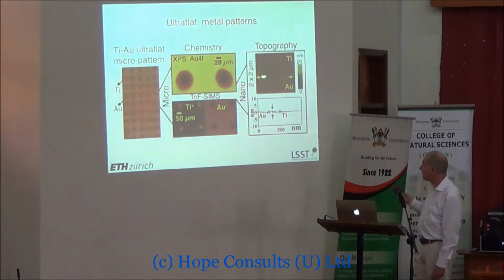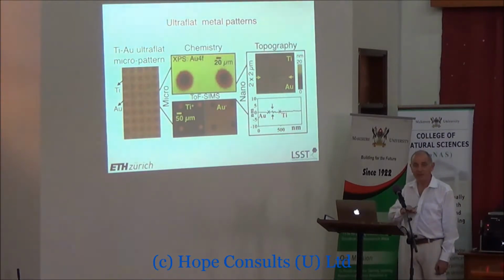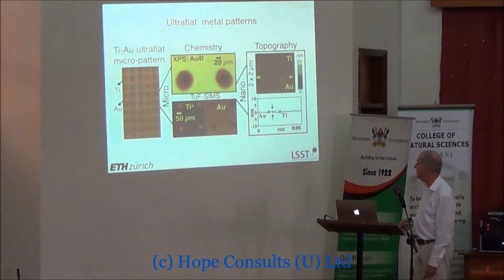And we use atomic force microscopy in order to look across the interface between the titanium and gold just to see how flat it was. You can just about see the interface, but it's on the 1 nanometer level. So we really have a very flat surface, which we can now functionalize with chemical means.